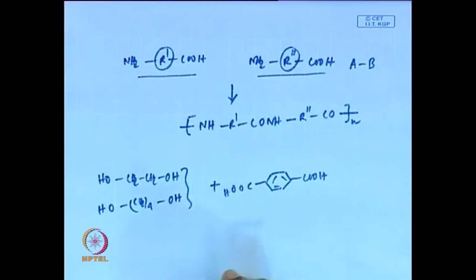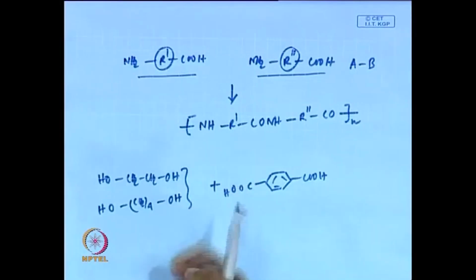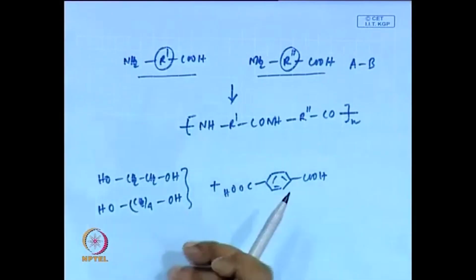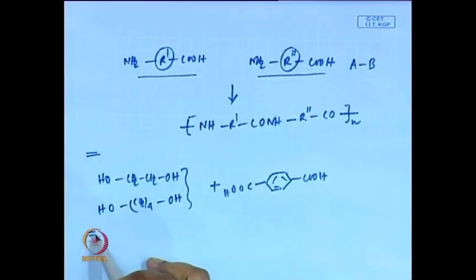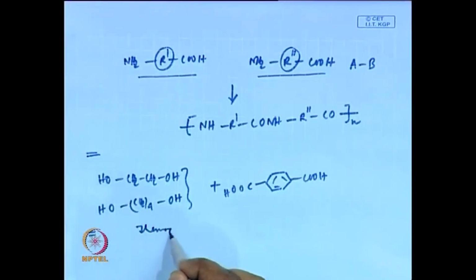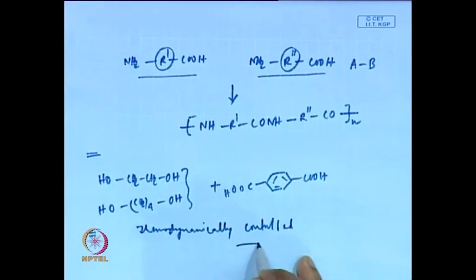Now, in the normal step polymerization reaction, because this is a thermodynamically controlled process, the byproducts also take part in the reverse reaction and the intermediate chains also take part in exchange reactions between them. So, they are always reshuffling during the entire reaction, with exchange happening between the chains. This means that if the reaction is thermodynamically controlled, then you will always land up with a completely random copolymer.